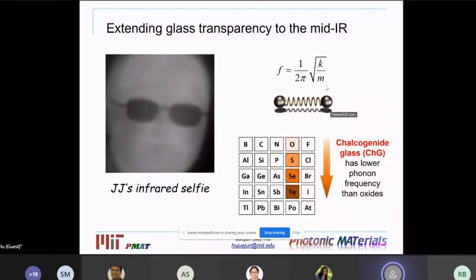So now, if you move from oxide glasses to chalcogenides, you now have heavier constituent elements. So this increases the m in the denominator. At the same time, because the chemical bonds between the chalcogens are weaker compared to those in oxides, you also reduce the k in the numerator. So the net effect is that these chalcogenide glasses have a much lower phonon frequency compared to oxides, and this underlies their broadband transparency in the infrared region.